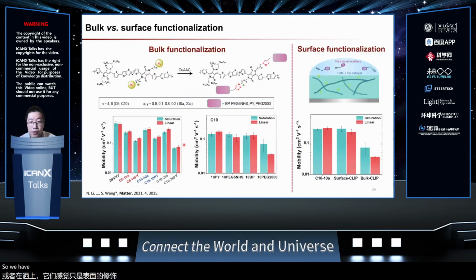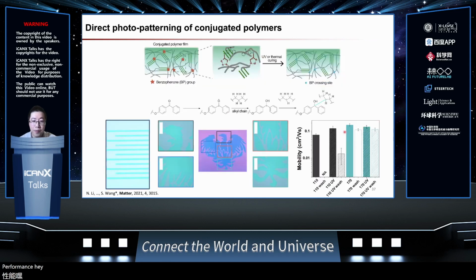So we have demonstrated that using this design, the performance is well maintained, both for the bulk functionalization that changed the polymer structure entirely, or only on the surface of the thin film with even less influence on the performance. Okay, so then by combining this, we have demonstrated two possibilities of realizing new functionalities in this current work.